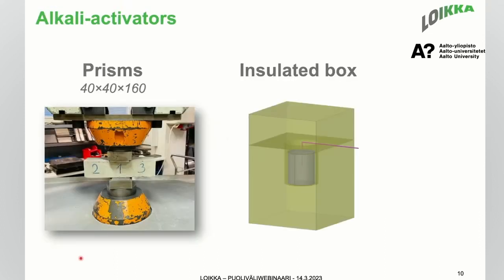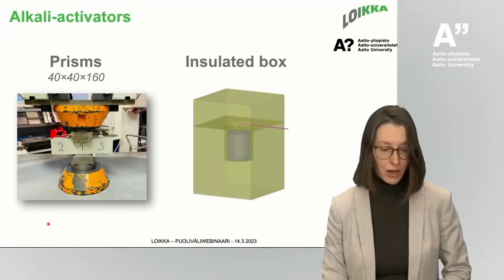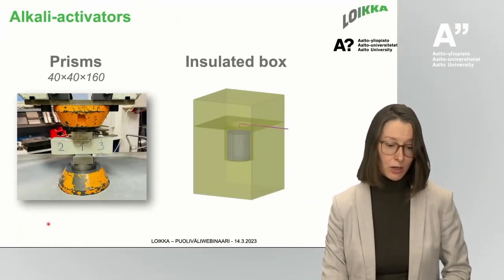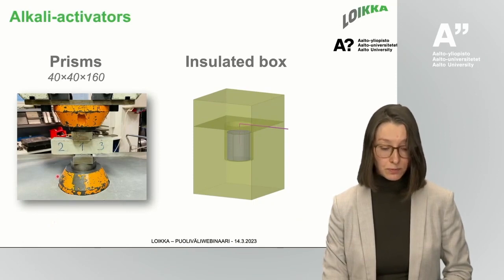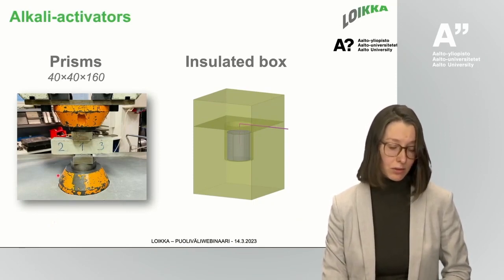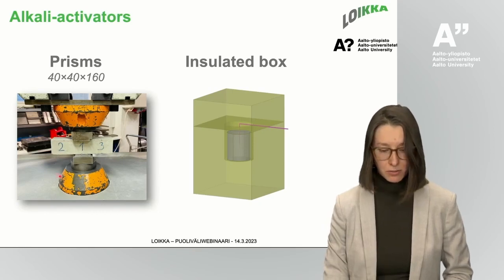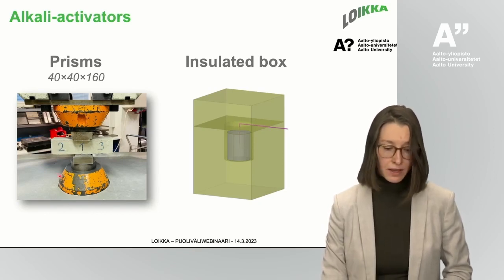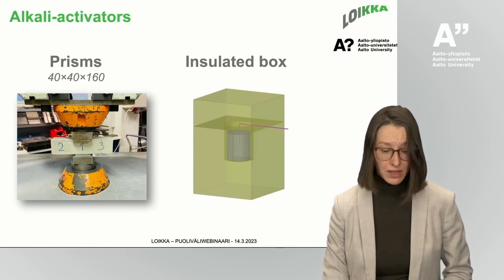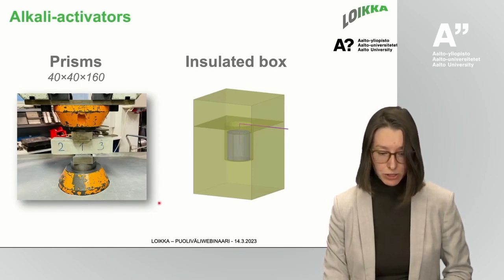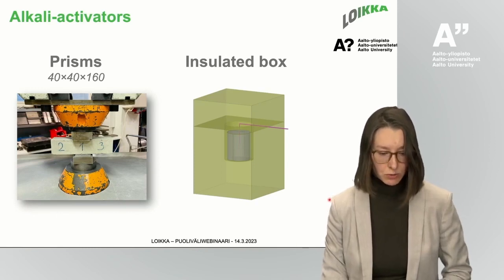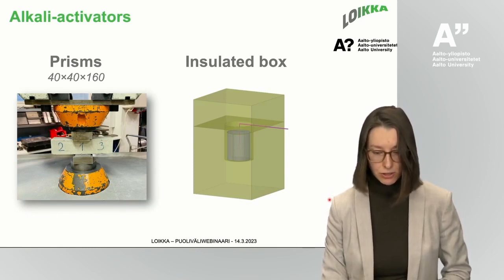Alkali activation. To simplify our testing procedure, we used prisms for testing the compressive strength. It also allowed us to increase the number of specimens. For prisms, we used cement paste, and we also measured temperature development through an insulated box, which allowed us to simulate semi-adiabatic conditions.